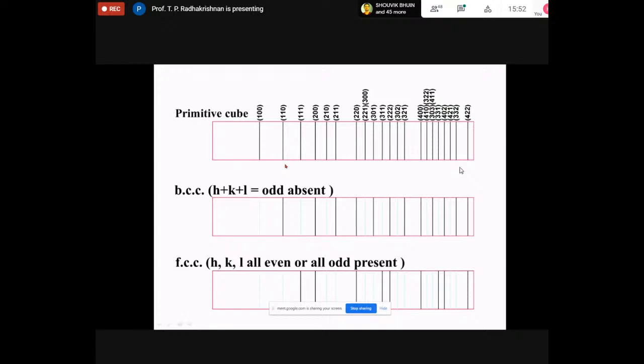Now, what is that? If I have a primitive cubic structure, I will see reflections, the scattering coming from 100, 110, 111, and so on and so forth. However, if I take an FCC crystal, I will see that there are diffraction patterns coming only from certain particular lines. For example, the 111 line is there, but 110 and 100 will not be there. When I did the indexing, if you remember, I did not get these indices. I got 111, I got 200. I did not get 210, 211, but I got 220, and so on. So there is a very unique fingerprint for this.